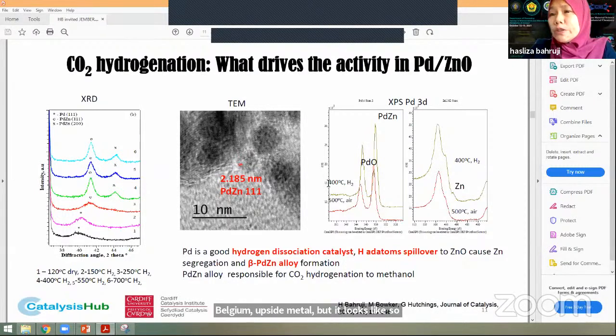But when we reduce that at 400 degrees Celsius, we started to see the shift of the binding energy towards much lower binding energy. It tells us that there is a change of electronic density of palladium, which gives us indication it produced palladium zinc alloy. The same thing with the XPS analysis of the zinc LMM spectra shows the formation of palladium zinc alloy by the formation of reduced zinc species here at 490 eV.